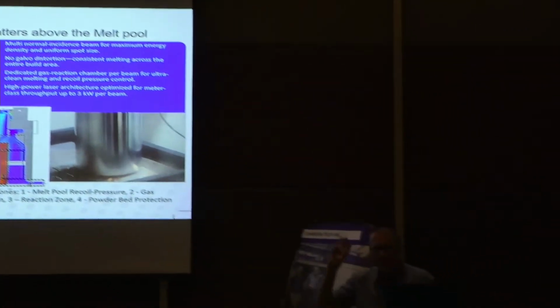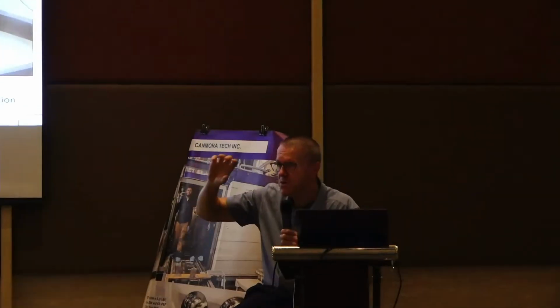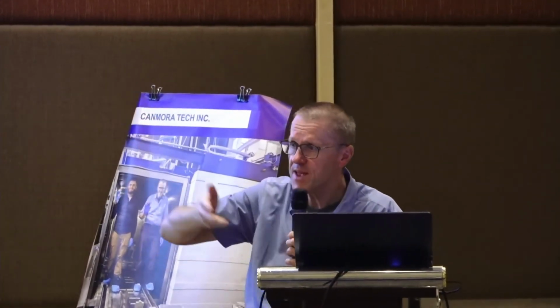So the first level was to have this laser beam always operating in the sweet spot. You do not get porosity. You can melt the exact parameters. You have constant velocities. The line energy is constant. The angle is constant. Also the volumetric melt pool, the volume that is described around the melt pool is constant. It's not a changing number. So that's why we have it this way, just to keep the conditions during the process equal.